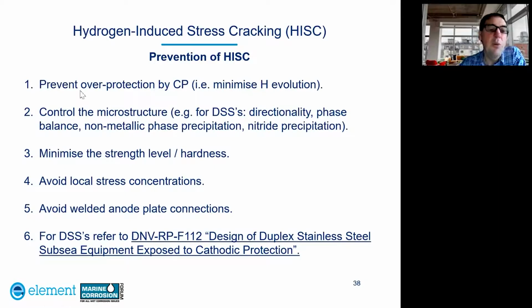So thirdly, you want to minimize the strength level and the hardness, and also avoid local stress concentrations and avoid welded anode plate connections. So finally, for duplex stainless steel, there is a recommended practice for HISC, which is RP F112, and this is a design of duplex stainless steel subsea equipment exposed to cathodic protection.